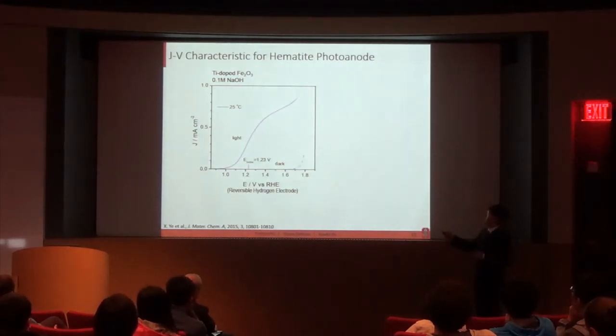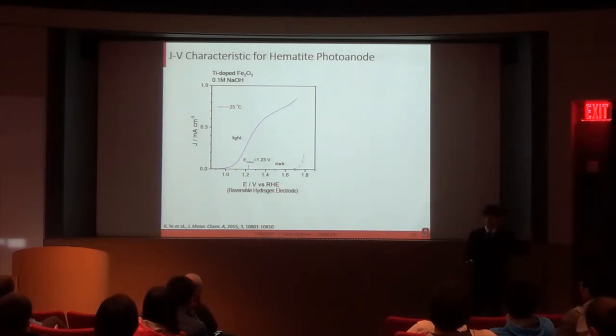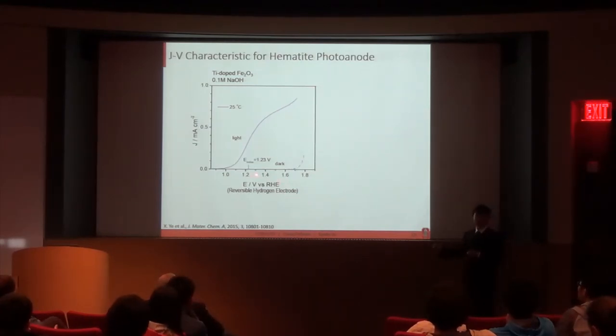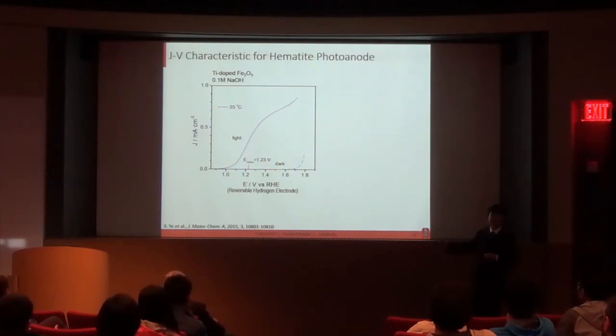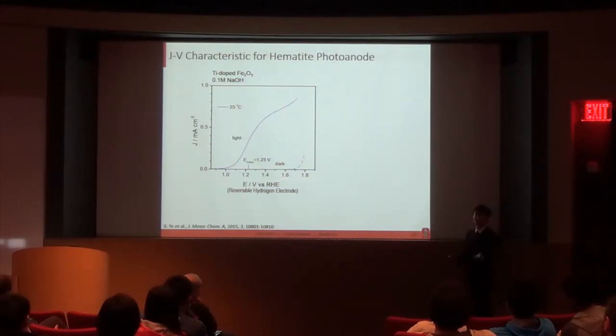So let me show you the JV characteristic of the hematite photoanode. I'm going to show you this kind of JV plot several times throughout my talk, so let me explain some details. The x-axis here is the bias that you apply between the photoanode and a reference electrode, which is a reversible hydrogen electrode in this case. The y-axis is the current density, which is the total current divided by the projected area of the photoanode. Also labeled in this plot is the redox potential for water oxidation, or oxygen evolution reaction, which is 1.23 volt at room temperature. As you can see, the dark current arises much later than this potential, indicating an overpotential that is needed to overcome the reaction barrier.